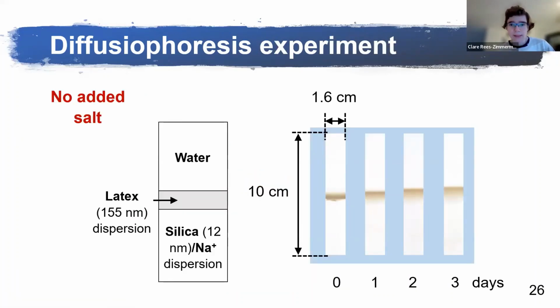Now I'm going to show you some example experimental results. You can see some images of the tank on the right of the screen. On the left is a schematic of how this experiment was set up. The top layer is a thick layer of deionized water. Then there's a thin middle layer of latex dispersion, which looks milky to the camera. And at the bottom, there's a silica sodium dispersion, which the camera can't see. You see from the photos that over time, the latex layer moves upwards, that is, down the concentration gradient of the silica. This is supportive of this being a diffusiophoresis process.